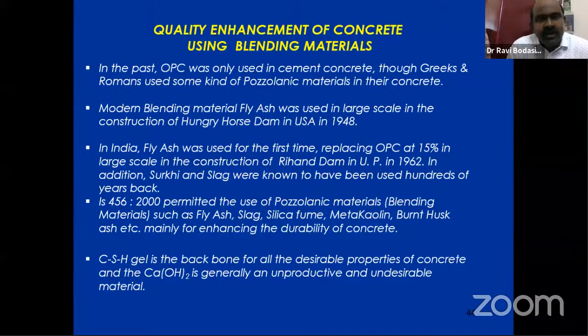Why? Because as common studies say, for manufacturing 1 kg of Portland cement, 0.5 kg of carbon dioxide is released into the environment. So in earlier days, we used only ordinary Portland cement. Imagine 300 kgs of cement, then immediately 150 kgs of carbon dioxide is released into the air. So how much the environment is getting affected. To compensate, the code now allows 15 to 35% replacement with fly ash, and for GGBS a minimum of 25% to 75%. We can replace the OPC content.